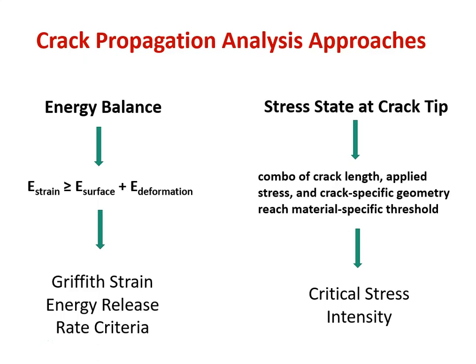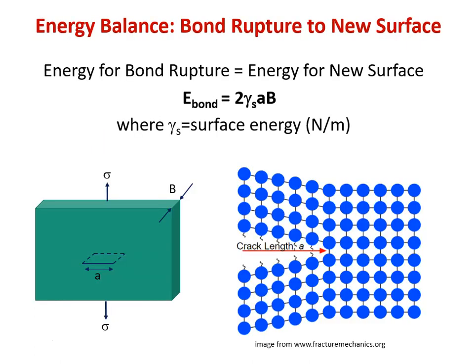So that's where we'll do most of our examples, and we'll define a term called the K1C, relating stress state average in the material to the average flaw size and whether or not a crack will spontaneously propagate. We're going to start with energy. So boy, we can go right back to our first discussion of a bond energy for this. It keeps coming back to bonding. We can think about the onset of failure, or the criteria for fracture, as whether or not we have added enough mechanical energy to a material to form a new surface by breaking bonds. So the energy necessary for fracture is the energy for bond rupture, which we can also think of as the energy to create new surfaces.